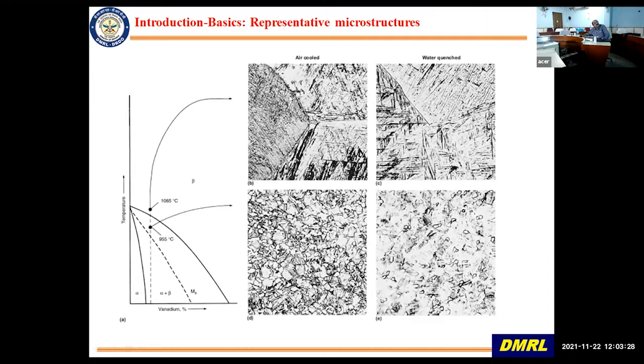In titanium alloys it is very difficult to make out, even if you do TEM and all, which is martensite and which is alpha. They both have the same crystal structure, with very slight difference in the lattice parameters. Then if you deform in the alpha plus beta region and heat it, and cool it, you get again globular alpha, and the transformed beta region can be very fine transformed beta, like in the top, and then you get globular alpha whenever you do deformation and heat it.